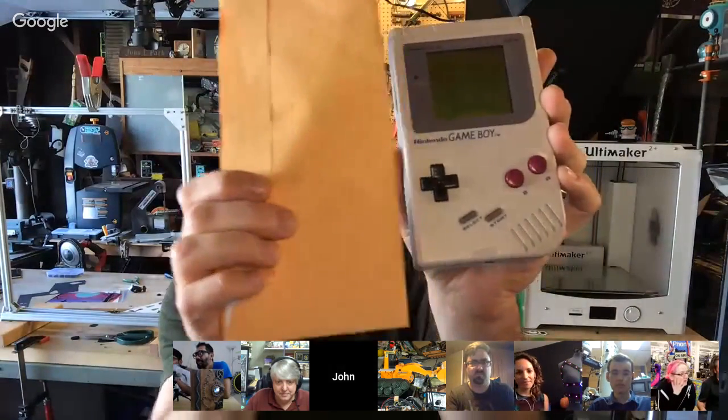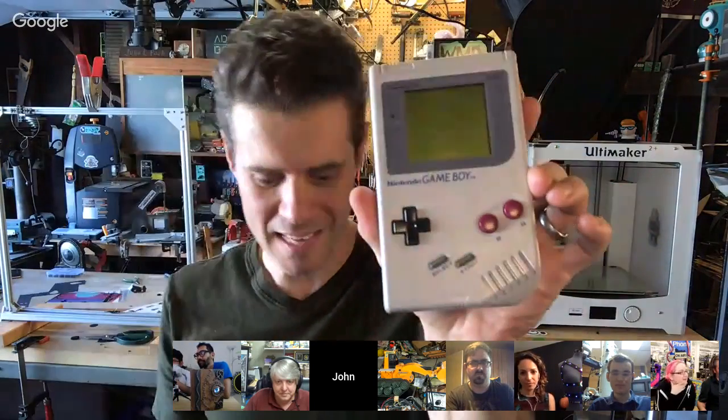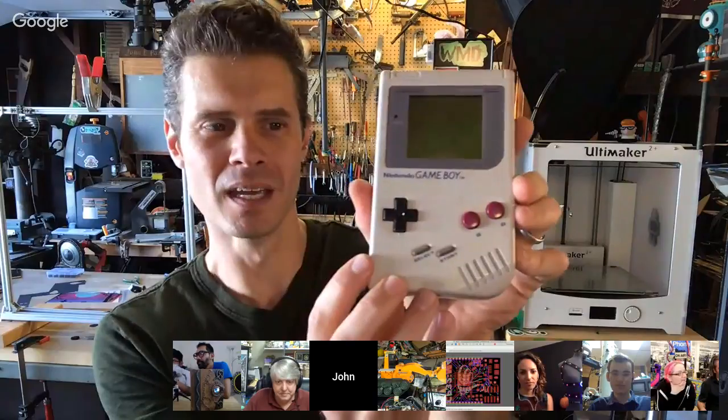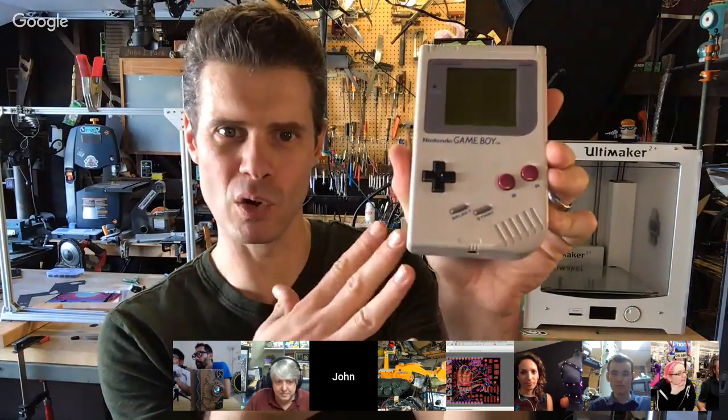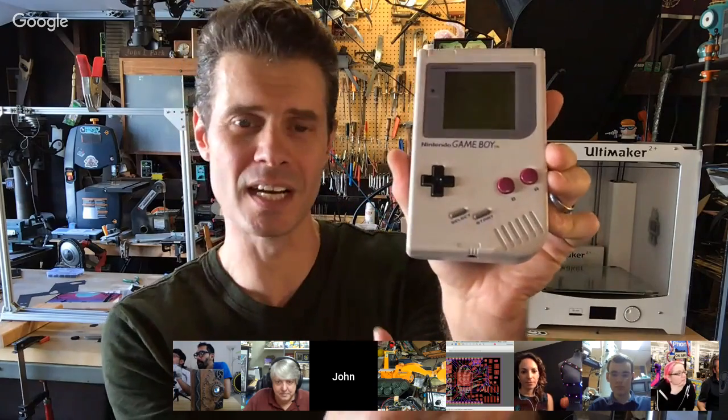The nice thing is that when I started, the color of it was basically like this, because you know what happens to this ABS plastic. There's bromine in there to make it fire retardant, which over the course of time and UV sunlight rises to the surface and yellows it.